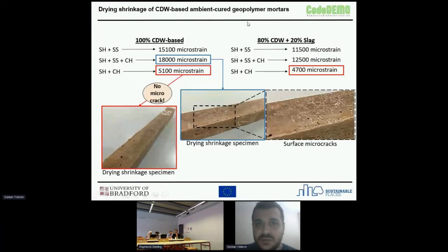Another issue in the case of geopolymers or alkali activated materials is the drying shrinkage. This is also another issue in traditional concrete mixtures, but it becomes more pronounced in the case of geopolymers. So depending on the use of different types of alkaline activators, we were able to terminate, or not terminate, but limit the drying shrinkage strains significantly. Depending on the type and utilization rate of your alkaline activator, you could see that the microstrains forming as a result of drying is significantly different.